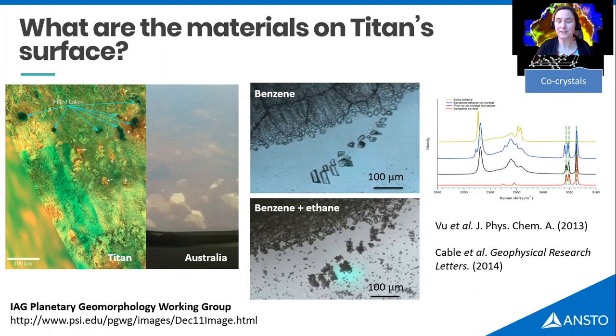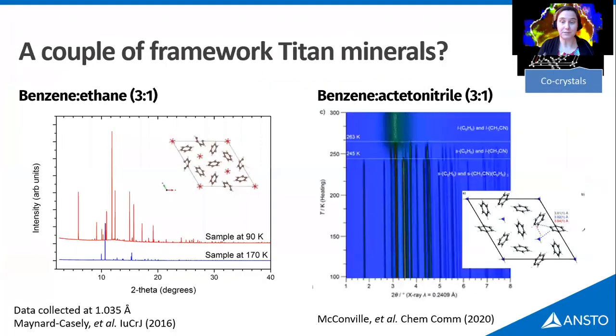A number of years ago, the group at JPL who started this whole field had a look at this and saw that when you interact benzene with ethane, you get quite a big change. They studied this with Raman scattering, and we were able to then do some diffraction with that, and it revealed quite a wonderful framework structure. This is our benzene ethane 3-to-1 co-crystal, where the benzene forms a framework and the ethanes live down the channels in that. This is what we thought was potentially the first Titan evaporite.